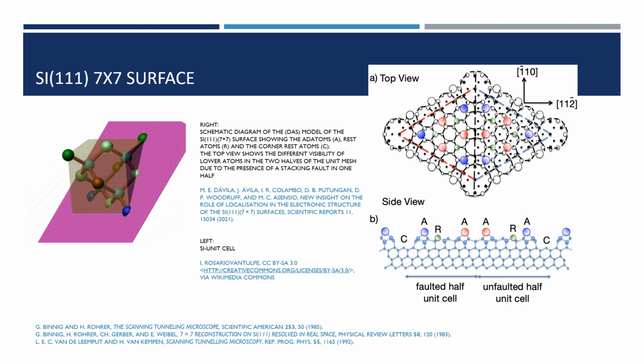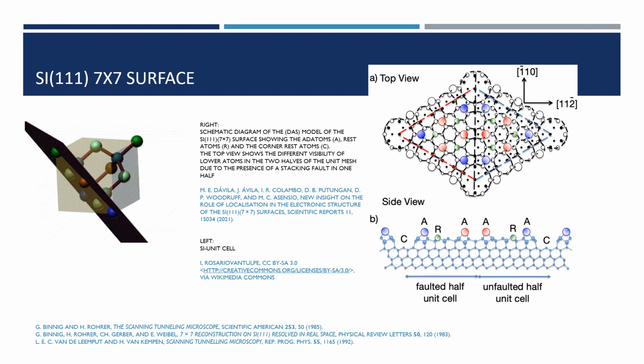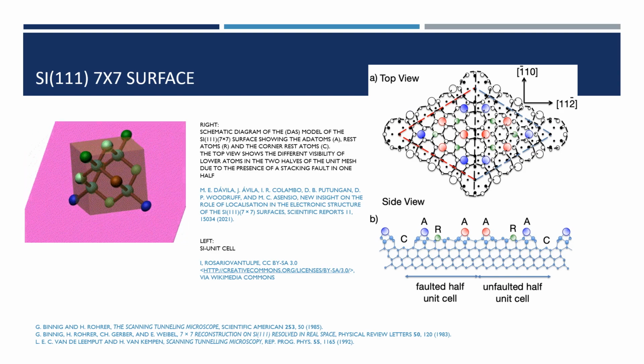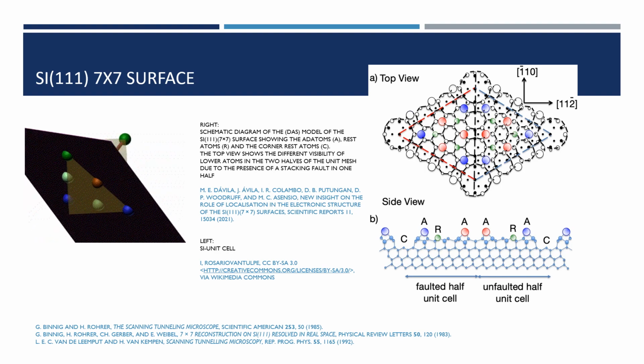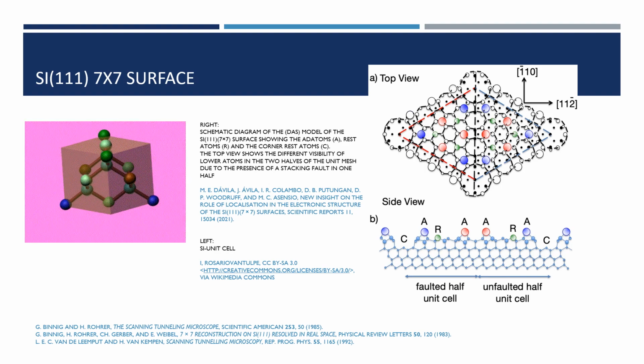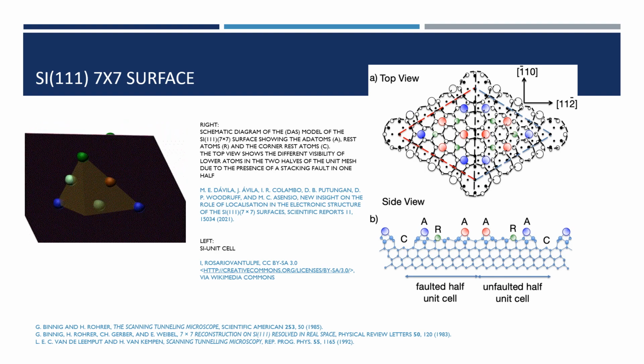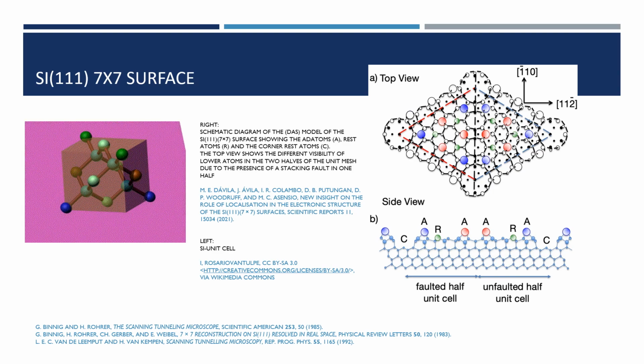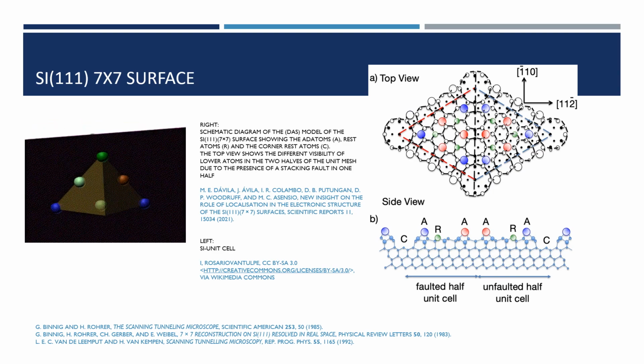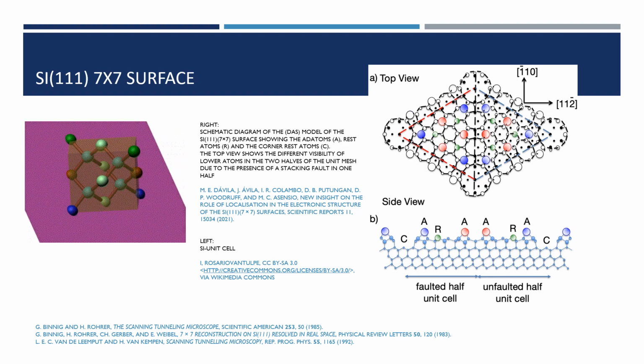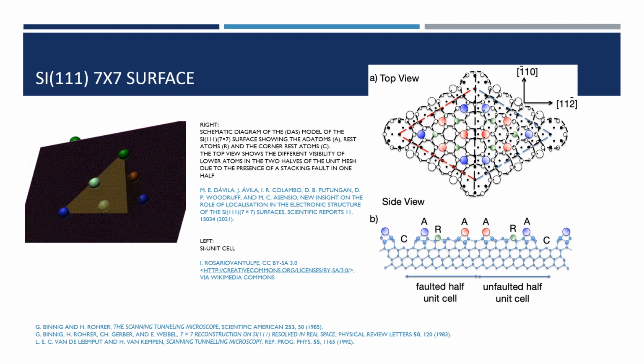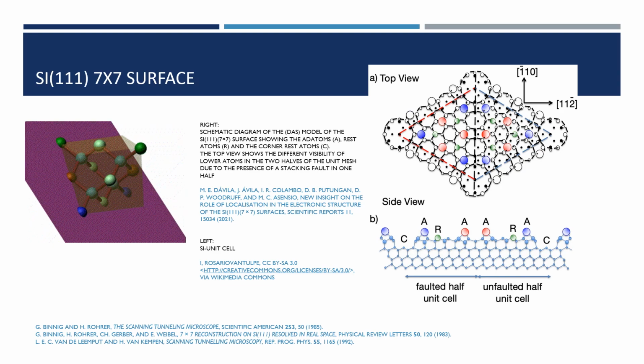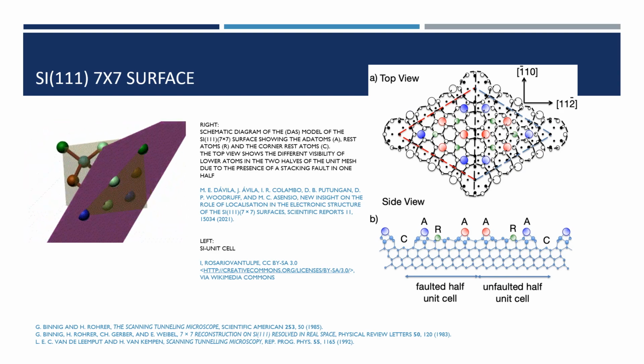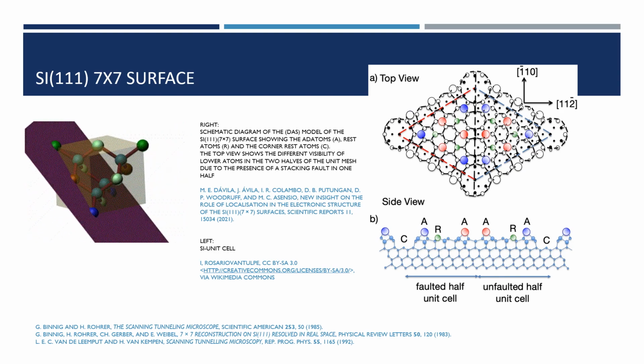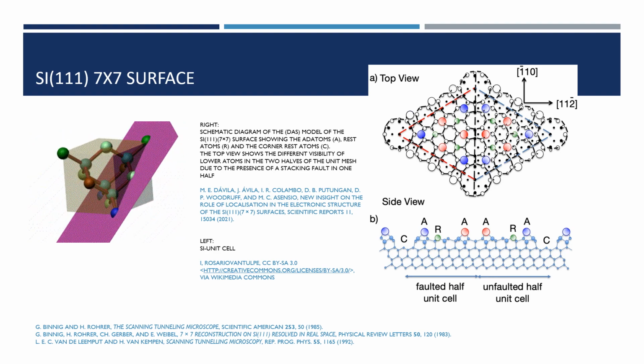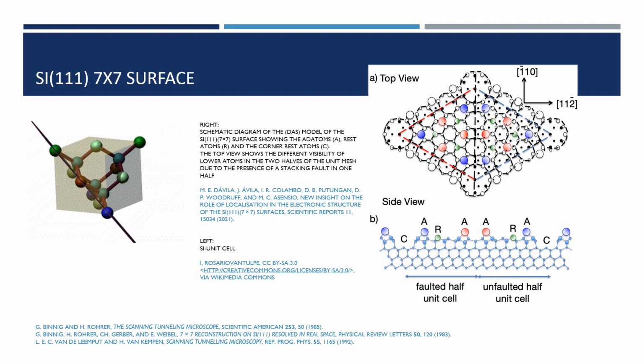A popular research object of the scanning tunneling microscope are semiconductors, as I mentioned. In particular, the study of the complex silicon-111 7x7 surface. This diamond-shaped unit cell of silicon is called 7x7 because each of the 4 edges of the cell measures 7 atomic distances. You can see it on the right. Each 7x7 contains 12 bumps, which could not be visualized up to this point, and each bump corresponds to a single atom. The bulk layer within a silicon crystal is shown on the left, and this unit cell contains only 2 atoms. This purple area is a 1-1-1 intersection.